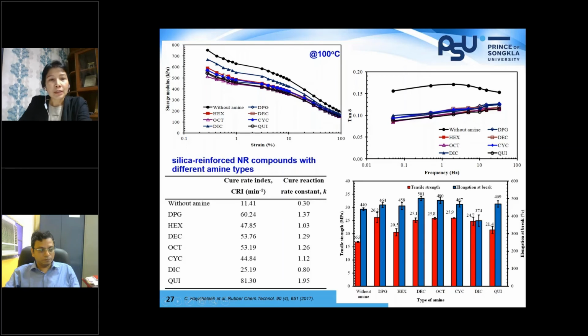So we see that different types of amine give similar behavior. We see pretty close storage modulus that changes according to strain. Only DIC, with two cyclic structures, this is a bicyclic structure, gives a higher Payne effect. Once it is vulcanized, we have a clearly lower tan delta compared with the compound without amine.